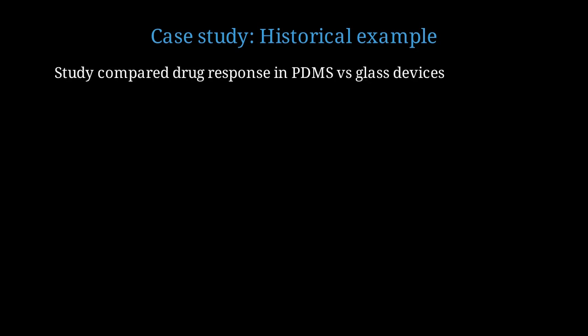Let me share a historical example that illustrates how serious this problem can be. A research group compared the same drug response assay in PDMS devices versus glass devices. In PDMS devices, the EC50 appeared to be 10 micromolar. In glass devices with identical cell culture, the EC50 was 10 nanomolar. 3 orders of magnitude difference caused purely by the device material. The PDMS result was completely wrong and would have led to incorrect conclusions about drug potency.